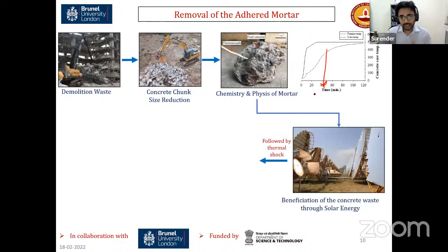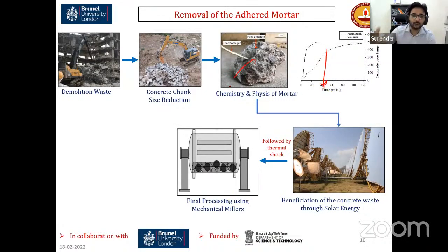So what we are doing, we are exploring the options of using concentrated solar energy, followed by, so you heat it up and then you remove it, cool it for 24 hours. So there will be some thermal shock also. And then this mortar becomes very, very weak. And then you just have to remove this weakened mortar. You can create some mechanical stresses over it with the help of the ball mills, right?